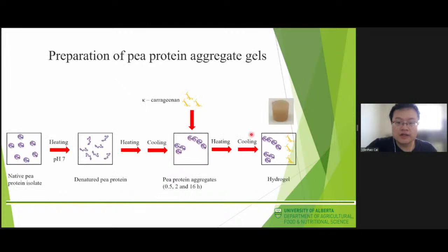In this work, heat-induced soluble pea protein aggregates were obtained prior to the addition of κ-carrageenan, so that negatively charged κ-carrageenan would not interfere with the unfolding and the aggregation of the pea protein.